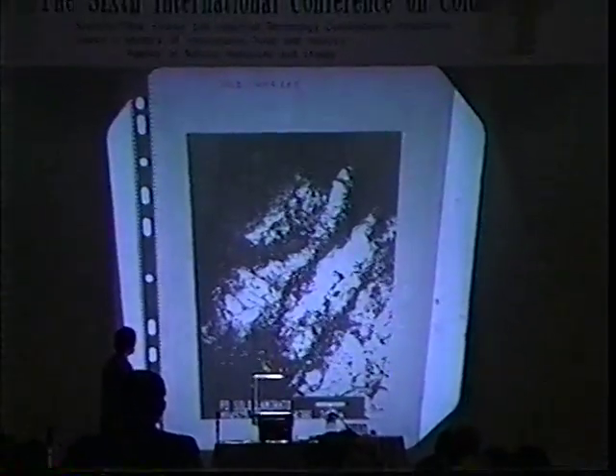In our study, we try to modify the metallurgical status of the metal. This is a cold-worked palladium foil, where we performed the lamination starting from 0.7 millimeter thick foil until 0.15 millimeter of thickness. And we see a very large concentration of defects. Then, after heating for 1 hour at 900 centigrade, we have this arrangement of the materials. And if we anneal more, we see that the lattice rearranges with the nucleation of grains again.